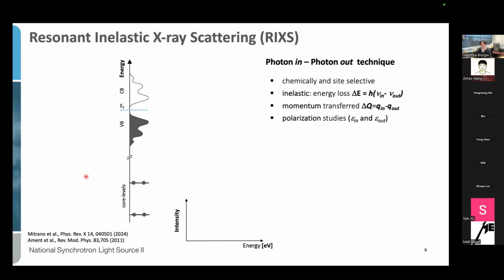So let me briefly introduce this technique then. Resonant inelastic X-ray scattering is a photon in, photon out process. To perform this technique, we need very specific conditions based on a synchrotron accelerator and on a beamline to produce monochromatic X-rays. So we shoot our monochromatic X-rays to our sample, and those need to be tuned in energy to resonate with a very specific transition in our material, for example, to promote a core electron into an open energy level in the conduction band. This step actually on its own corresponds to the X-ray absorption of the material under study, for example, as it's shown here for a copper-based oxide.